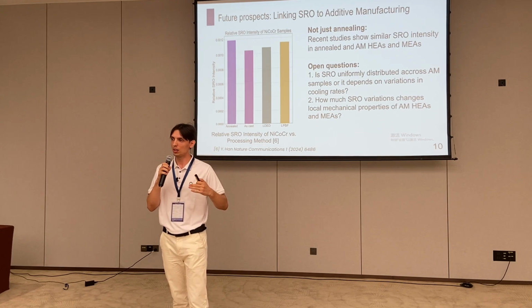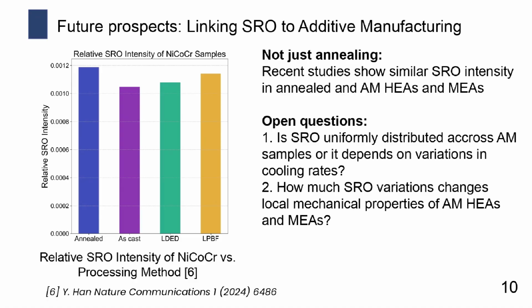And this brings us to two questions. Because additively manufactured samples are cooled at different cooling rates, it is assumed that there will be non-uniform distribution in short-range order. So methods such as the one presented are essential to find the exact values of the short-range order. And also the second question which arises is how much short-range order variations change the local mechanical properties in the additively manufactured high-entropy and medium-entropy alloys.